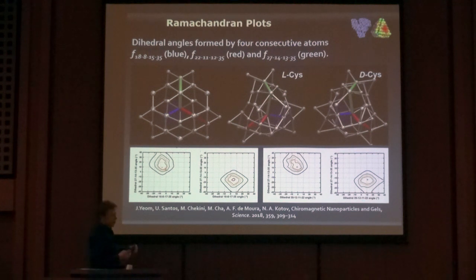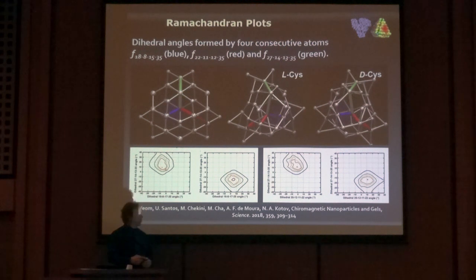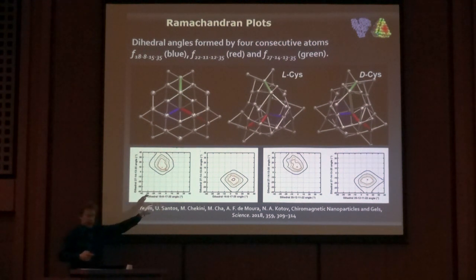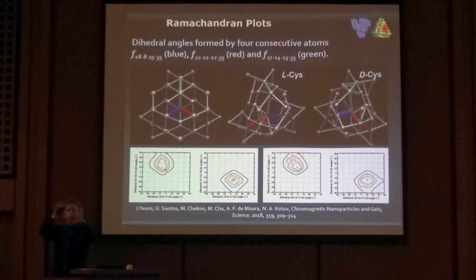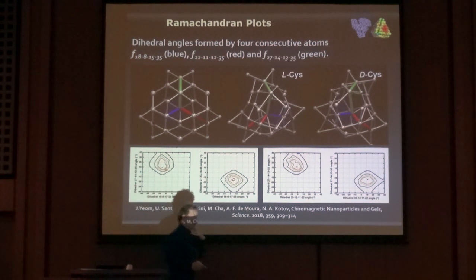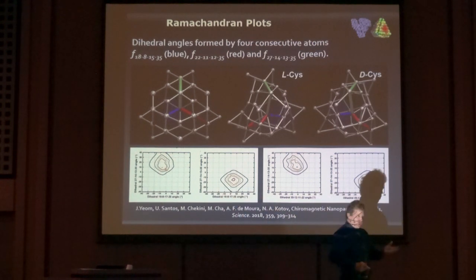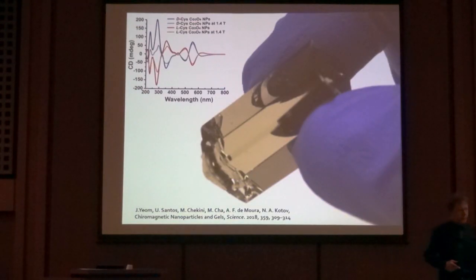One of the very interesting points of coincidence between the proteins and nanoparticles can be identified by the use of the so-called Ramachandran plots, which are used to look at the conformations of the proteins. They are certainly applicable here and indicate the same screw dislocation, the same distortions as we observe for a lot of proteins. Why is this important from the technological standpoint?